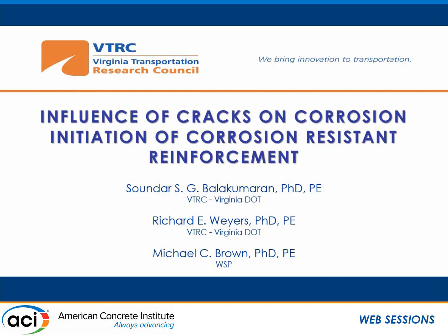VDOT has been employing a number of crack control strategies, such as using internal curing with lightweight aggregates, putting an upper limit on the cement content in the concrete mixes, using shrinkage-reducing admixtures and fiber-reinforced concrete for locations where you need to arrest the size of cracks. But none of these would exactly eliminate the cracks entirely. But they do help in controlling the occurrence of cracks.